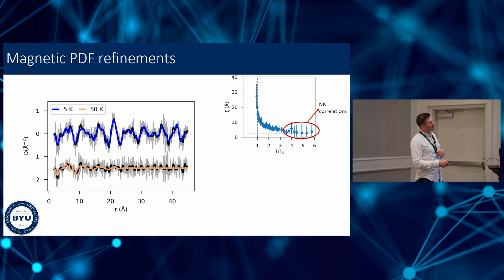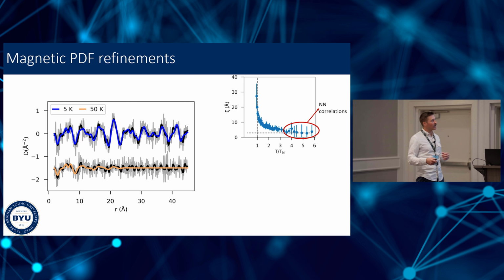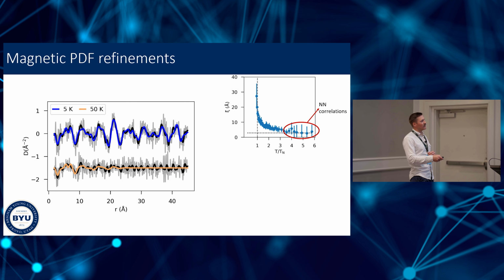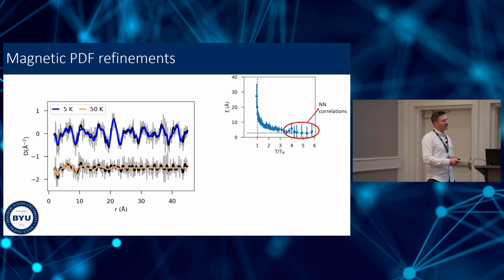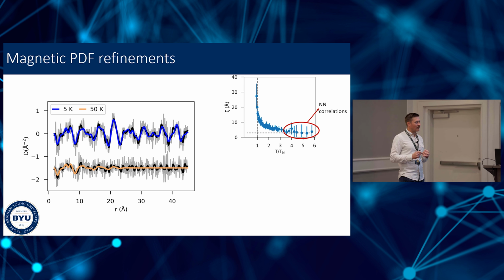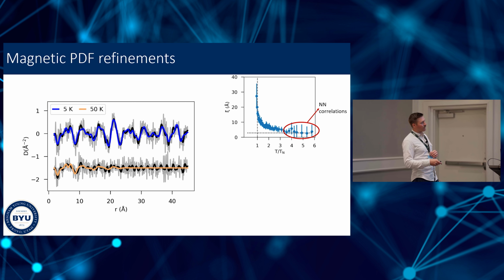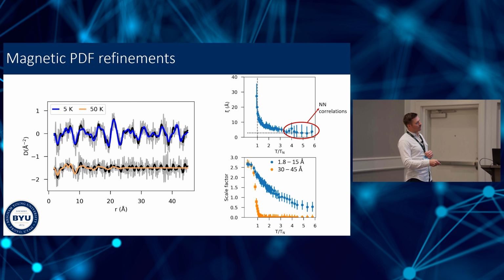And what we see is that the correlation length is really restricted just to the nearest neighbors at the highest temperatures. But as we lower the temperature, naturally, those correlations grow in spatial extent. So the correlation length increases and appears to diverge. When it gets to about 25 angstroms, that's when the long-range order kicks in. And then we get true, genuine magnetic Bragg peaks and long-range antiferromagnetic order. And this is what the local magnetic order parameter is doing right here compared to the average magnetic order parameter.